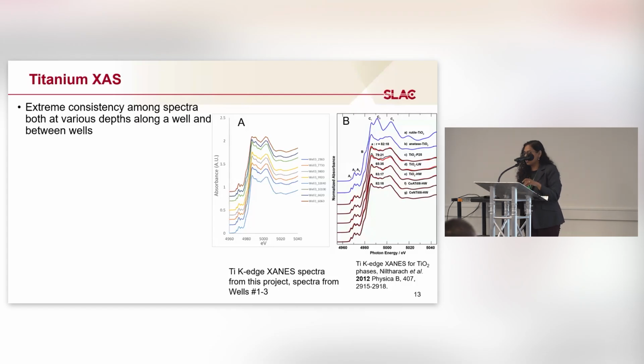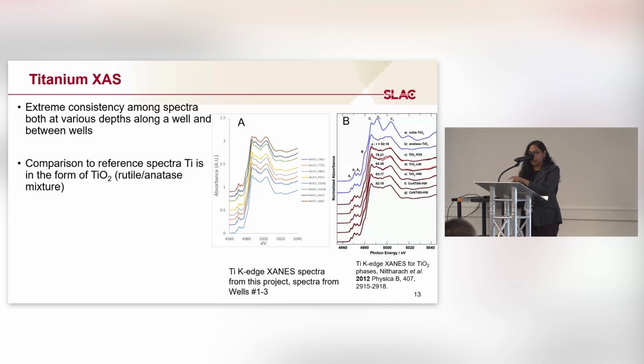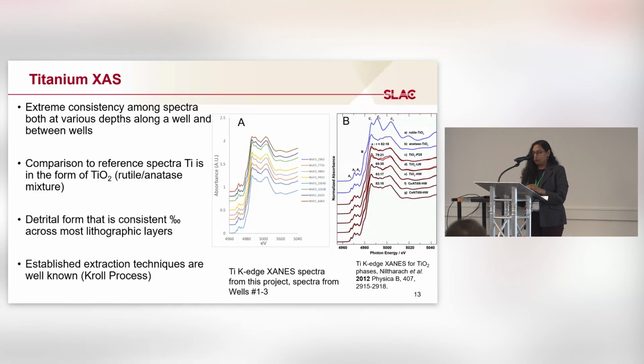And comparing our data to the reference spectra, it looks like titanium exists as a mixture of rutile and anatase. Whether it's rutile or anatase, it's still titanium dioxide, and there is a very established technique for extraction of these materials known as the Kroll process.